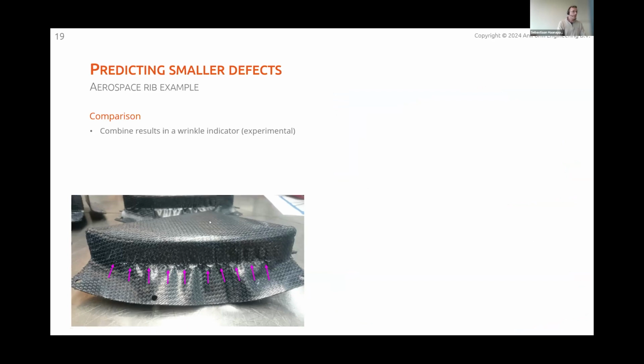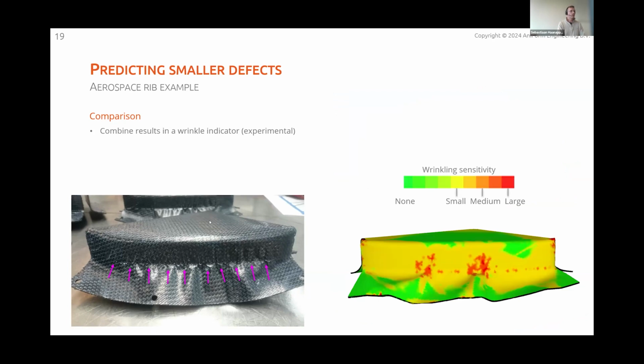That's quite indirect. You can make that task of analyzing a bit easier by using a wrinkle indicator. That is experimental yet, but can be used, and it gives you some kind of wrinkling sensitivity. Under the hood, it looks at the results I just showed you. So you get a big orange area where the wrinkle sensitivity is between small and medium, and the red spots say, well, there's quite a big chance you will have a wrinkle there. So I would say, yeah, the issued area is quite well indicated.